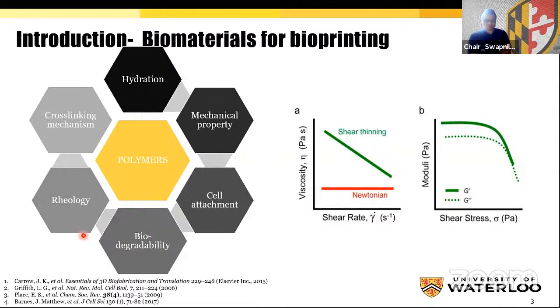Ideal bioinks must also meet the requirements for printability, such as resolution and pattern fidelity. Bioink with strong shear thinning is preferred. The low viscosity at high shear rates prevents clogging and shields cells from shear forces within the nozzle that can lead to cell damage. Once through the nozzle, the shear rate decreases and the ink thickens up again to hold its shape. In addition, the elastic modulus G' should be higher than the viscous modulus G'', as it avoids spreading and collapsing. To ensure high structural integrity and long-term shape fidelity, in situ cross-linking and instant gelation after deposition are also preferred.